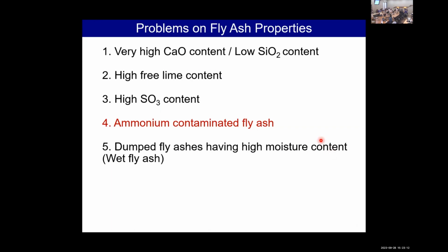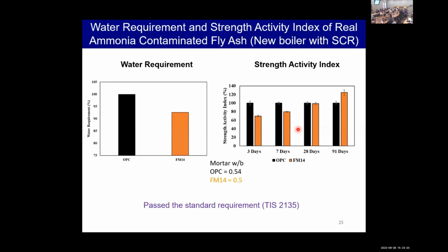Okay, next problem: ammonium contaminated fly ash. This one comes from the fly ash from boilers that use SCR technology to reduce NOx, right? For the process, we need to inject ammonia, and the ammonia can contaminate the fly ash. So in this case, we took samples from a boiler with SCR that may contain ammonia-contaminated fly ash, and tested basic properties like water requirement and strength activity index.